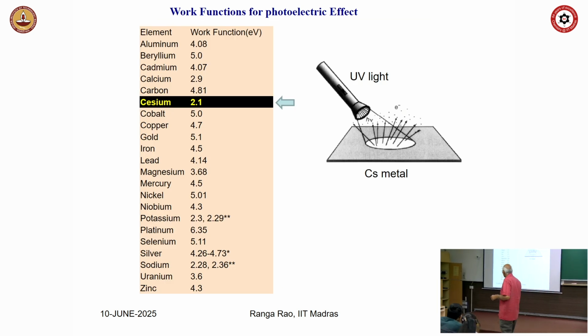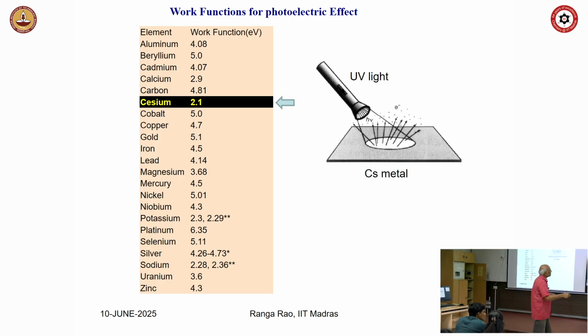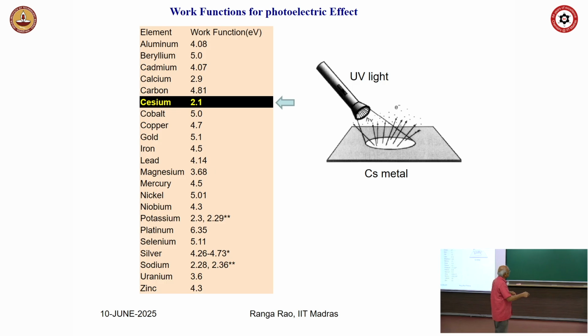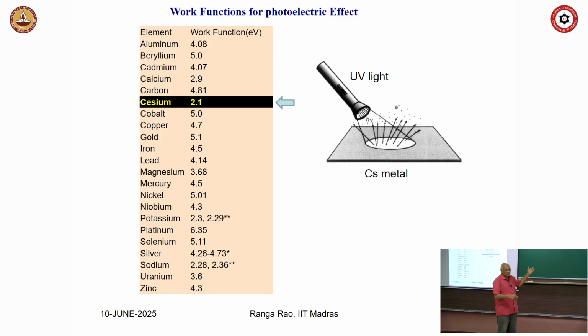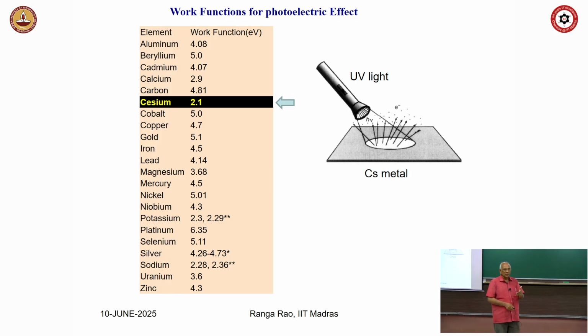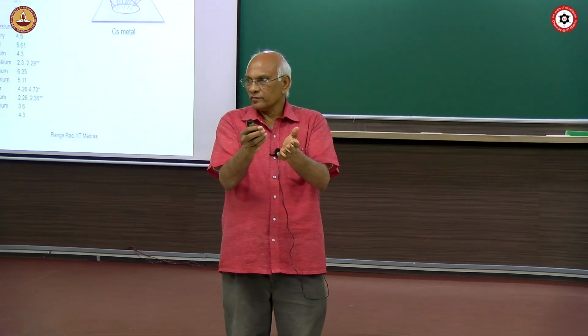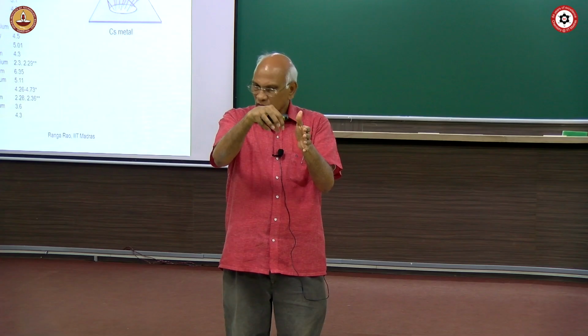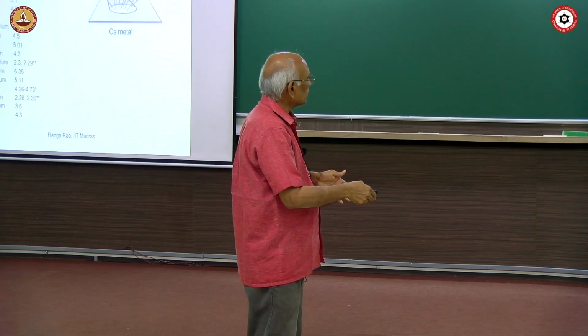Now, see, I have given you some of the values of the work functions here. In this case, for example, aluminum is 4.08, and as you keep going here, zinc is 4.3. The lowest one is cesium, 2.1. That's what we saw. Even potassium is around 2.2. You are getting photoelectrons coming out in the previous slide, right? So cesium 2.1, that's the lowest one. 2.1 is nothing but the UV region, UV light. You shine UV light on a cesium metal, you start getting electrons out, which can be demonstrated in the lab also. All that you have to have is some vacuum system, and to collect the electrons you have to have a photodiode to collect the electrons and show it. Okay, all right. So these are all work functions.